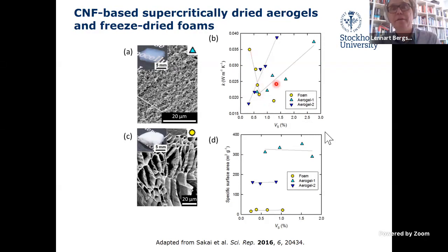On the other hand, the freeze-dried foams have an unexpected behavior where you have a reduction in thermal conductivity initially as the density increases.